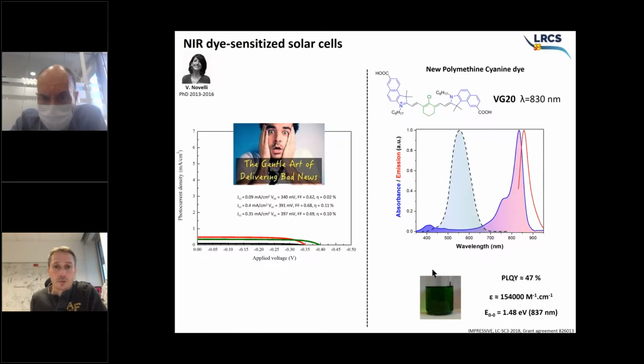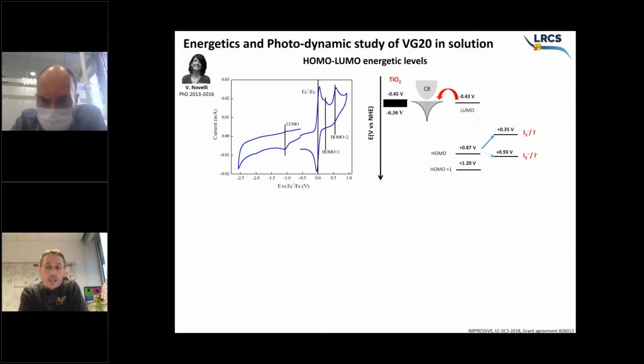This is because of the molar extinction coefficient. In terms of energetics, this dye is interesting because when you reduce the band gap of the absorber, often you start to have problems either for the injection or for the dye regeneration. And this is really what limits the near-infrared dye solar cell: you come into competition between injection and regeneration. So actually, this is the HOMO level that can be regenerated by the iodine/iodide redox couple.